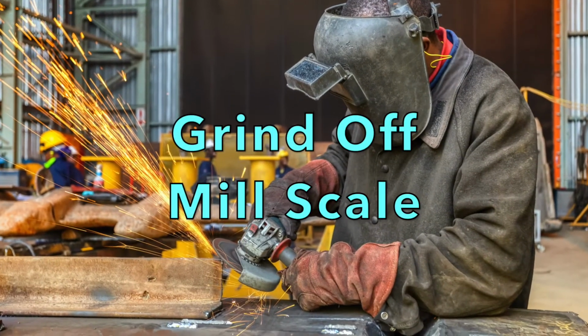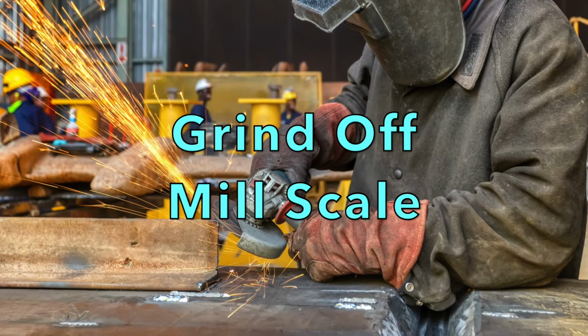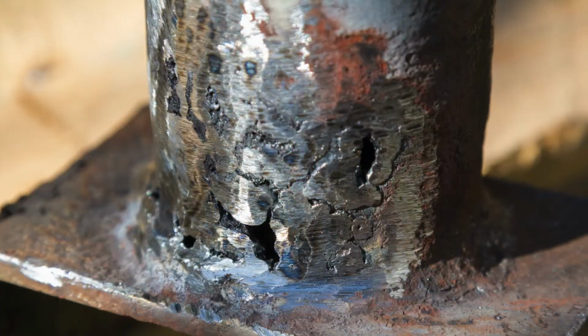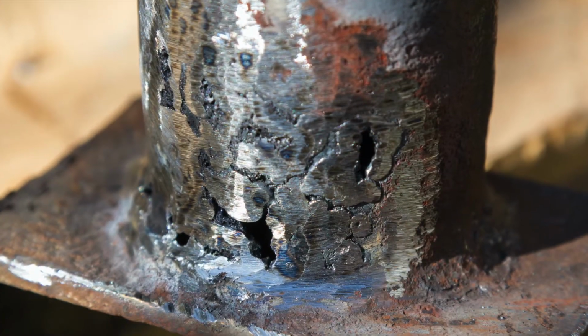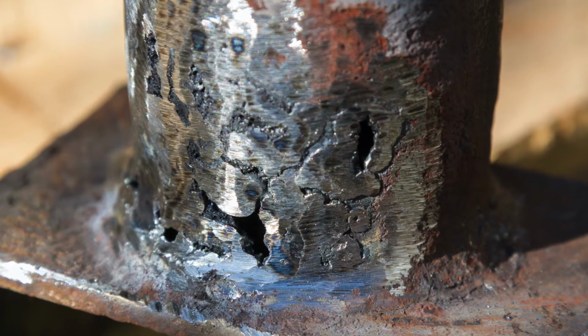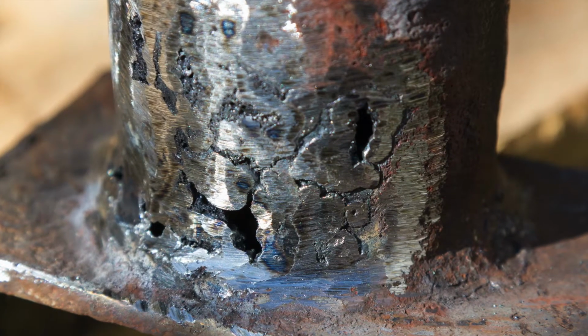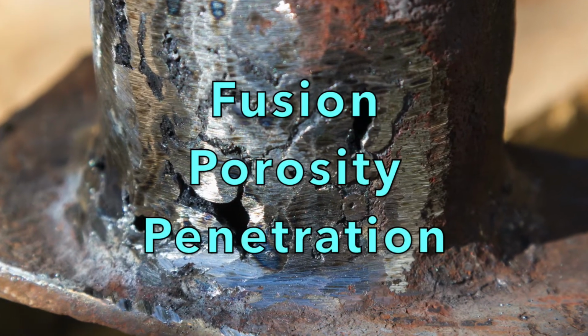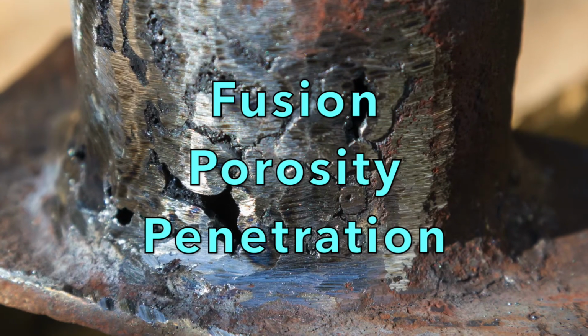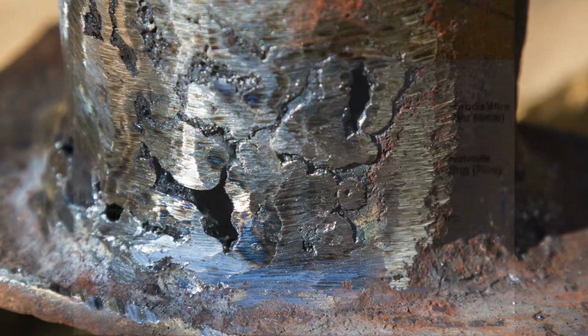It is highly recommended to grind off the mill scale prior to welding. Mill scale has a higher melting temperature than the steel itself. When welding over the mill scale, it can cause serious issues for the weld, such as lack of fusion to the base metal, porosity, or incomplete joint penetration.